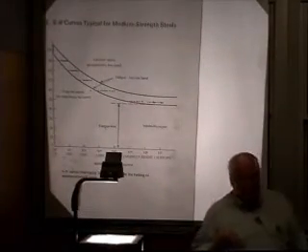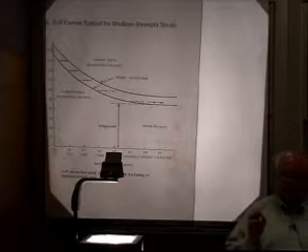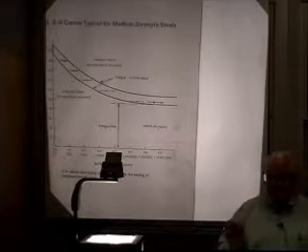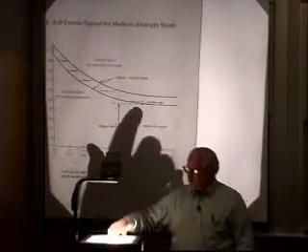Okay, you might have a flaw in a typical steel. If you just go take some garden variety steel off the shelf, you'll have flaws that are around 4 to 10 thousandths in size as a maximum flaw size. Those are just the inclusions in the steel. 4 thousandths is about 1.5 human hairs. 10 thousandths is about 4 human hairs in size. Not very big flaws, but basically if you went and put that typical flaw size in and then calculated that